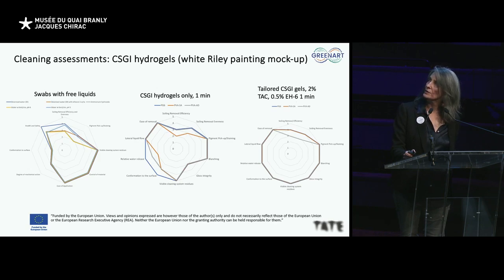This is just 3 that I've cherry-picked for you. On the left-hand side, we have a number of free liquids with cotton swabs, your classic way of cleaning. In the middle, we have the same systems with some of the CSGI gels, just with deionized water for 1 minute. And then on the right-hand side, we have the tailored CSGI gels, which are generally the new ones, with triammonium citrate and EcoSurf in low amounts. And the general gist of these is the larger the shape or the larger the star, the better the system. So you can see there's an improvement from the left to the right-hand side as we tailor and test these gels and aqueous systems.